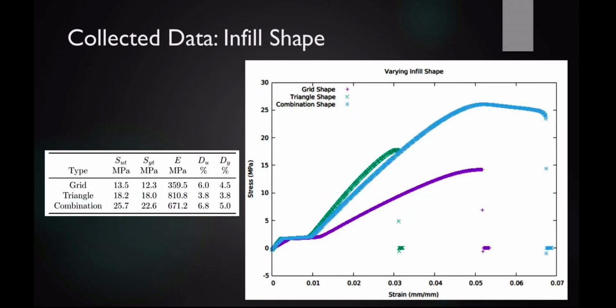Lastly, the infill shape, which is by far the oddest of the graphs. Starting with grid, which is the standard shape, again, we see the toe region. Still, it's a polymer property. It's not a structural thing. That's always going to be there for these samples. The grid infill shape, which is the standard, really just underperforms. There's no other way to put it. It has the lowest Young's modulus, yield strength, and ultimate strength, and that's all there is to say about it. It's the standard, but it shouldn't be the standard.